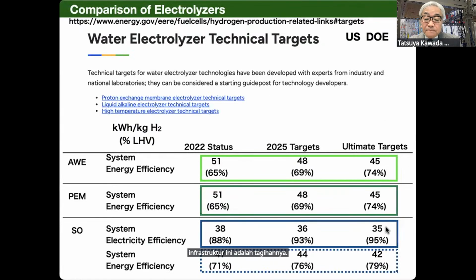So the target values are in kilowatt hour per kilogram hydrogen. For low temperature systems, the ultimate target is 45 kilowatt hours per kilogram hydrogen, but only solid oxide has 35 kilowatt hours per kilogram hydrogen. So it is much different. Of course, it is assumed that the water vapor is supplied. And a similar thing is also in the EU target.